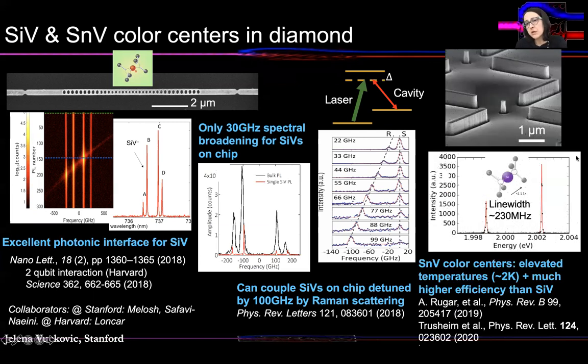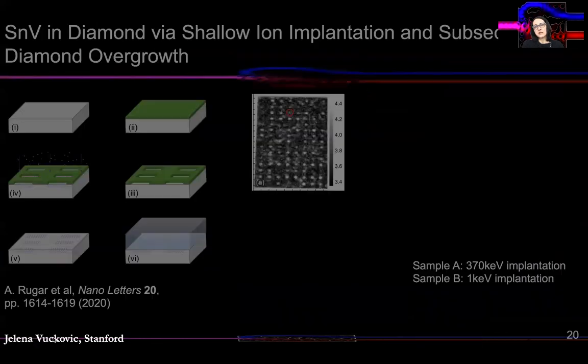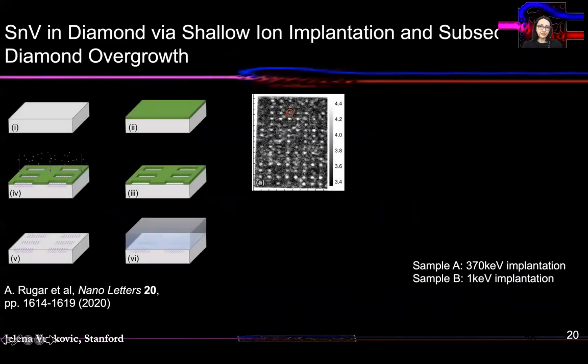And more recently, we've been looking into tin vacancy color centers in diamond, which are even more exciting than silicon vacancies, in my opinion, because they promise all of the advantages of silicon vacancies. But at elevated temperatures, you don't need to use dilution refrigerators as for silicon vacancies, and you also achieve higher efficiency than for silicon vacancies. Again, here you work with single impurities inside of diamond, in this case, or other semiconductors. So introducing them in a controllable manner is quite challenging, because that also means that you have to precisely control the position where you're introducing the impurity and control their environment.